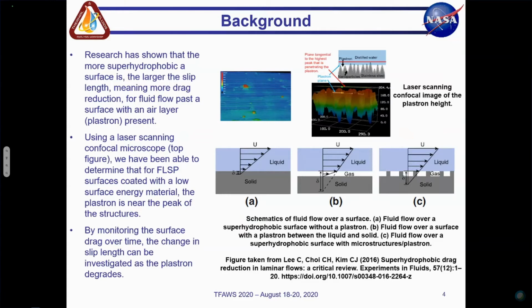And you can kind of see that in the bottom right figure with images B and C that's given. And then using a laser scanning confocal microscope here at the University of Nebraska-Lincoln, we're able to determine that when we have these femtosecond laser processed surfaces with microstructures, and we coat them using low surface energy materials, this air layer comes up to the peak of the microstructures. So that gives us somewhat of a height of the air layer that we have. And then by monitoring the drag over time, we can see how this slip length changes, which also will show how this plastron degrades.